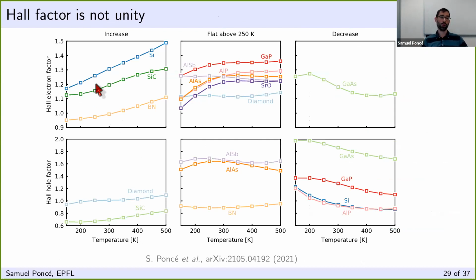And what I want to emphasize is that, first, in a lot of materials, the Hall factor is not 1. Therefore, it's important to take it into account if you want to compare with experiments. But also, it's temperature dependent. So the Hall factor, for example, increases in those compounds, decreases in those, and remains relatively constant in all of those materials. And the value goes from 0.6 up to about 2 in those materials.